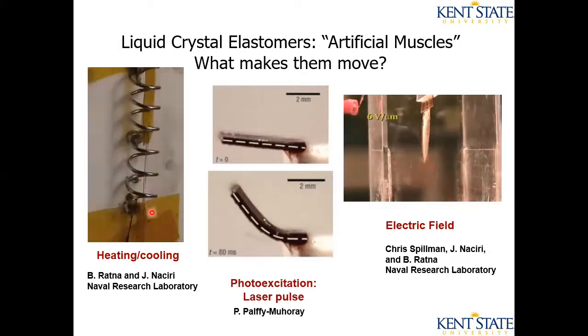So if you look at this thing, the liquid crystal elastomer is the little skinny thin object in the middle, and the yellow part is tape, which is causing it to be attached to something. And then what's happening is current is running in this coil, and so when you run current in the coil, it heats it up and it shrinks. And when the current is turned off, it expands. And that's kind of a puzzle. When I was a little girl, my mother told me when you heat things up, they expand. And this one expands when it's cold and shrinks when it's hot. That's kind of a puzzle.